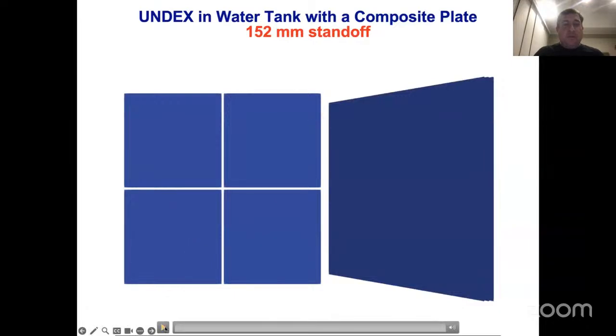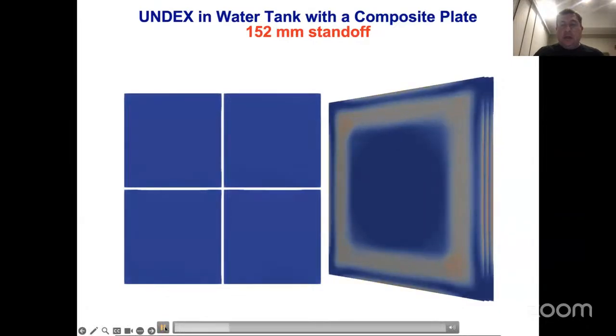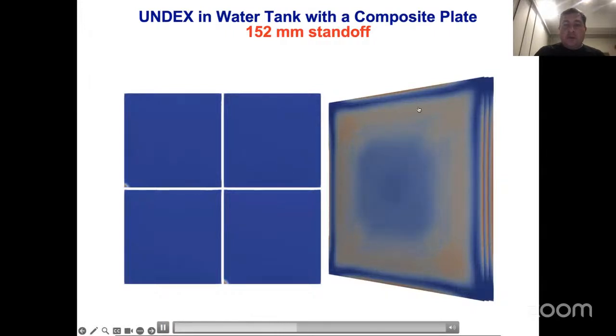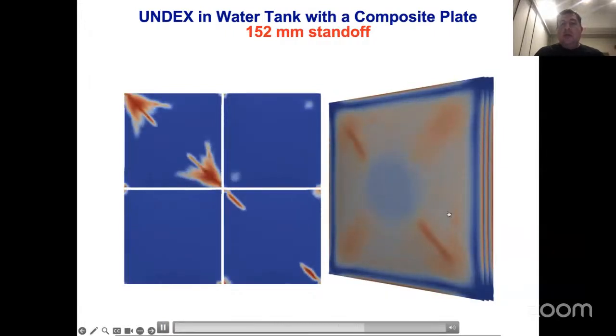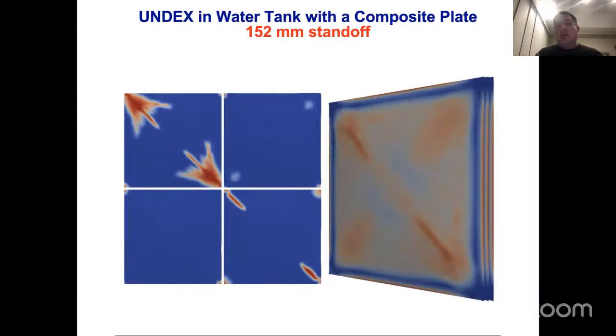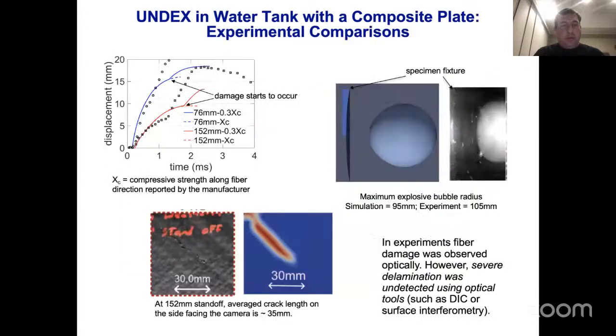This is 152 millimeter standoff. Again, delamination starts from the corners. Okay, once enough delamination happens, then the fractures start. So that's a behavior that our experimental group is observing, but it's kind of hard to do this with optical type techniques underwater. And so our high fidelity FSI tools with composite damage are actually able to capture this.